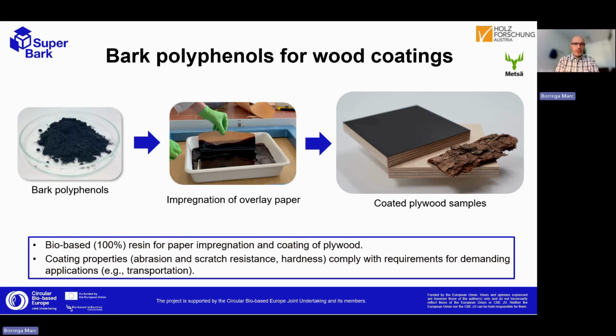Now, these polyphenols can be used not only to make a resin for adhesives, but also for coatings. This is an example of the coatings developed by our partner from Holzforschung Austria. So basically, they have developed a resin which is 100% bio-based. They use the polyphenols and a bio-based cross-linker. You can see in the middle image there's like a liquid, brownish liquid, which is the resin.